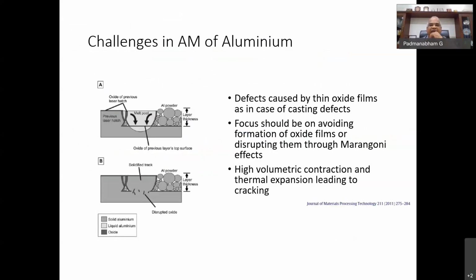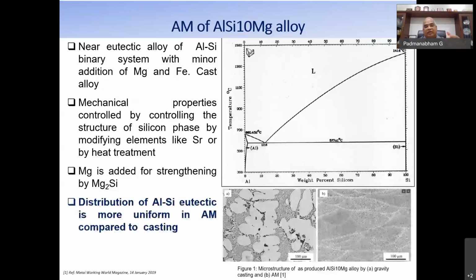Let us look at non-ferrous materials. When we handle aluminum, we have defects caused by thin oxide films. The focus should be on avoiding formation of oxide films, through Marangoni effects. And then high volumetric contraction and thermal expansion lead to other issues like stresses, etc. These are all issues. And one of the popular materials which is friendly with AM is aluminum silicon magnesium alloy.